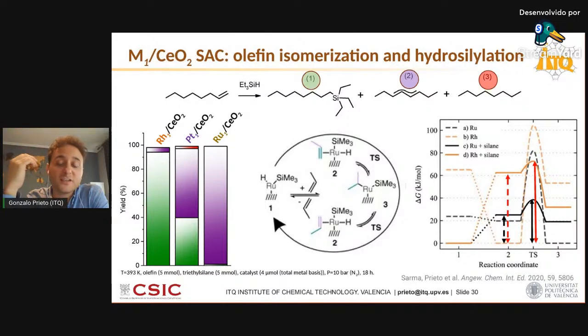Then there is the possibility to have just olefin isomerization, double bond migration, to have internal olefins from the terminal starting olefin. That's the product I depict as two, internal olefins in color purple. And finally, one can have this premature hydrogenation of the olefin, the undesired one, the most undesired one, to produce octane in this case. Then how do these three single atom catalysts behave? Well, we started testing platinum because platinum is the benchmark catalyst for this hydrosilylation chemistry in homogeneous catalysis. And platinum was active for both hydrosilylation and olefin double bond migration, as you can see here. To some extent, also to hydrogenation.